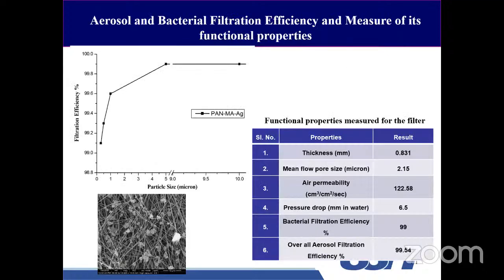Then we checked the filtration efficiency against bacteria and aerosol. As you can clearly see, for the aerosols, the overall filtration efficiency is about 99.54%. As you can see from the image, the aerosols, the PM 2.5 that entered through this membrane are being trapped between the fibers. We also checked the thickness, mean flow pore size, and the air permeability was quite high compared to the cartridge filters. The pressure drop was minimal, like 6.5 mm of water. And the bacterial filtration efficiency was about 99%.